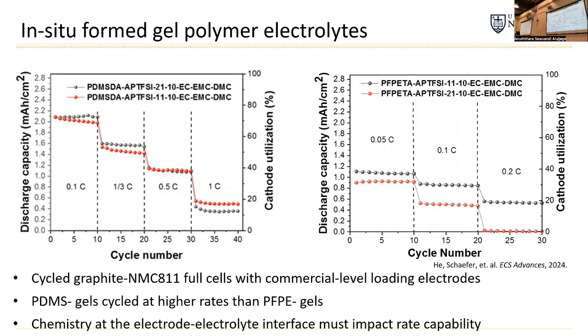Then our collaborators provided us with industrially relevant electrodes: high loading graphite anodes and high loading NMC811, a high voltage cathode material. We prepared cells with these very dense electrodes with this in situ polymerization. Overall, our cathode utilization is fairly low, but they were really impressed with it because there's no dissolved conventional salt in these. That means the only electrode particles that can be accessed are the ones where the plastic is nearby, unless there's any ionic monomer that's not polymerized. So the infiltration of the gel into the electrode is very important for these cycling studies.